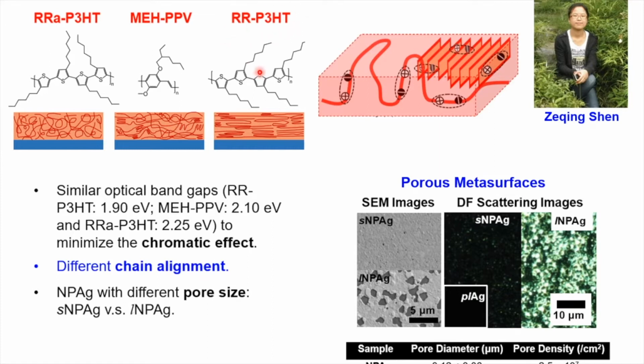And regioregular P3HT is very crystalline, typically with the main chain of the polymer lying in the plane of the semiconductor. And so in general, you can see that the excitons, just based on this, if you have amorphous polymer chains, they can be oriented in different directions. If you have crystallinity, you can get very strong orientation in the plane, in the case of regioregular P3HT, but you can also get interchain interactions that cause interchain excitons.